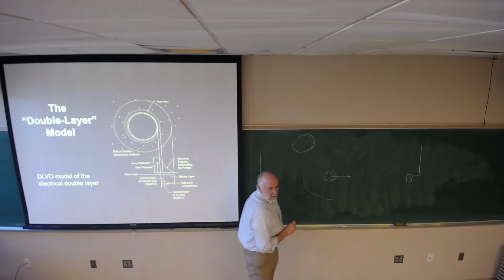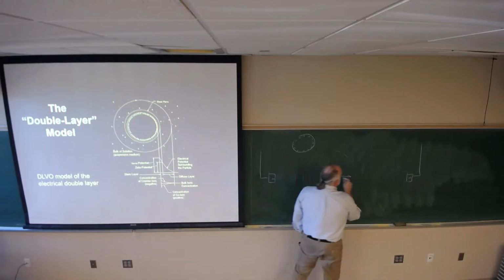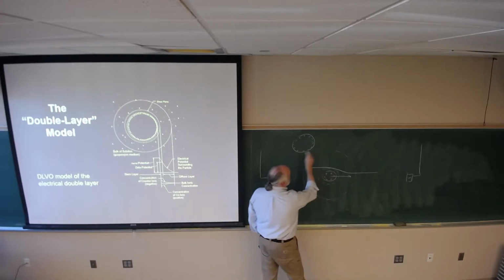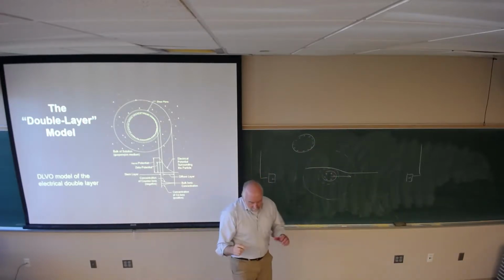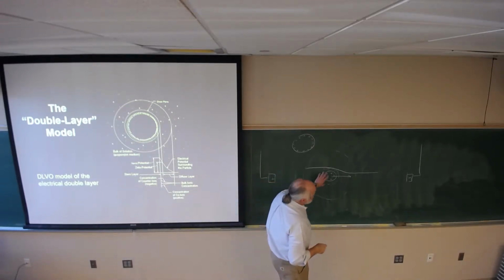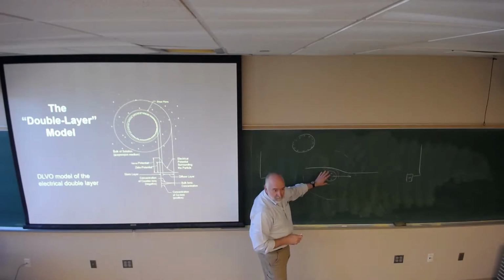And those ions get stripped off by the velocity of this particle moving through. And at the surface here, I have this layer of ions, about 3 ion layers thick, which is strongly held. And in the movement of this particle, they don't get pulled away. So instead, that layer of ions is fixed.